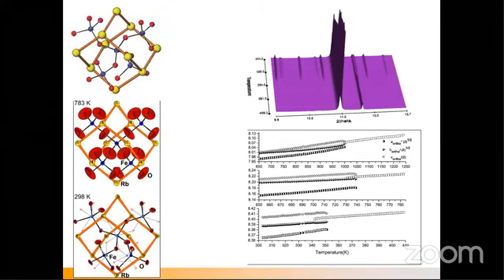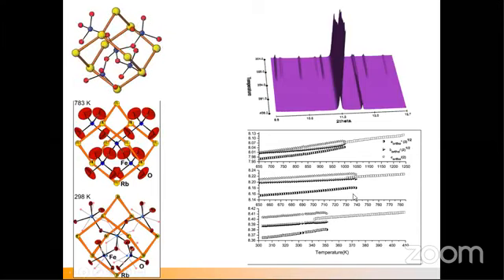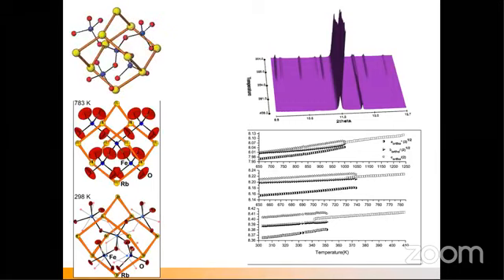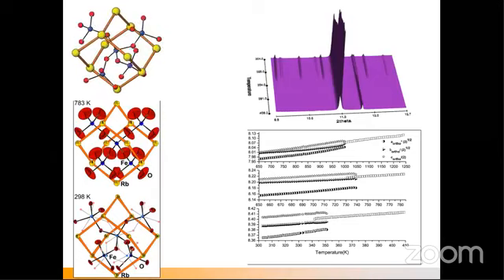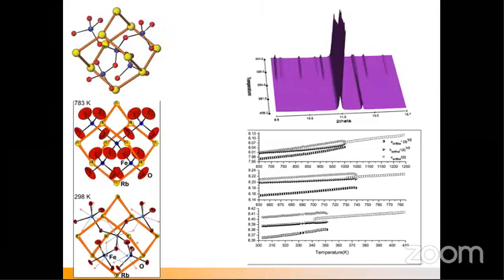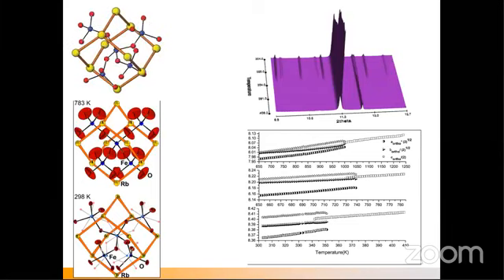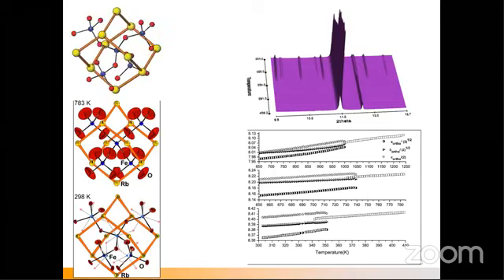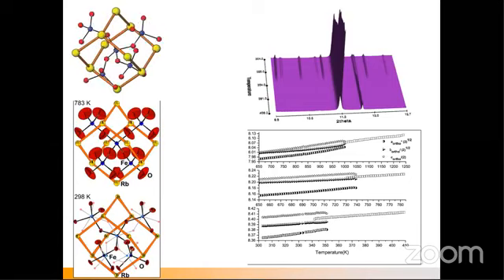The second method, as I told you, is through DSC, right, left. At certain temperatures, above 380 Kelvin, the phase is cubic, and below that the phase is orthorhombic. When it's cubic, A is equal to B is equal to C, so we have a single line. Below that we have an orthorhombic phase where A is not equal to B, not equal to C, and alpha is equal to beta is equal to gamma is equal to 90 degrees. One should know all these things, and one should easily calculate this information from single crystal X-ray diffraction and also from powder diffraction. I will explain how one can calculate the lattice parameter from the powder diffraction. At the temperature of around 400 K, in the right top blue picture, we have only a single peak that belongs to the cubic phase, and below that we have multiple peaks that belong to the orthorhombic phase.